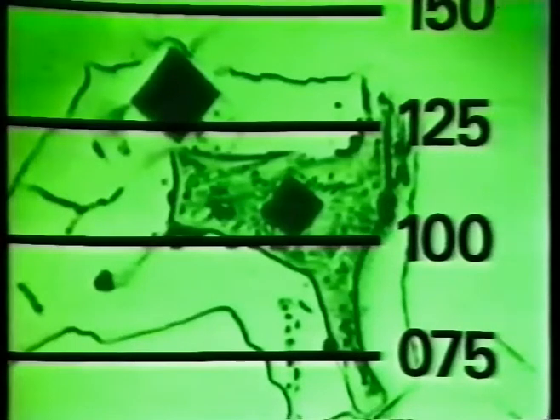This equipment operates with green light, but we've got a blue-grey region dead center, and in this region we can see that the indentation is quite small compared with the indentation in the matrix. So yes, we have got this type of material, hard particles embedded in a soft matrix. So it probably is these that are responsible for the superior performance of the old bearing.